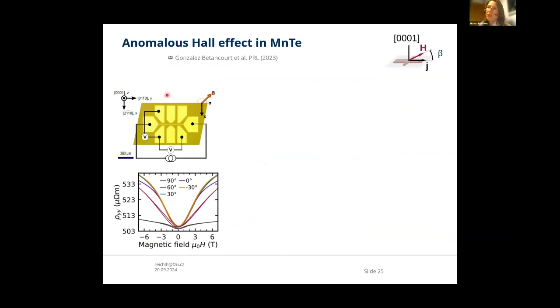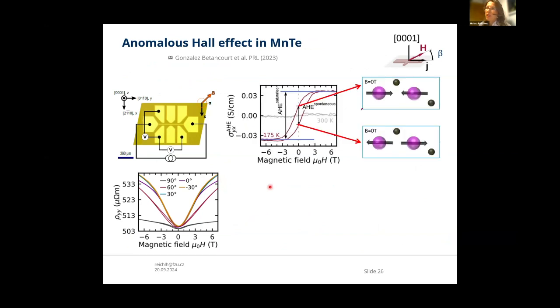Here we pattern Hall bars from the manganese telluride thin films, and we measure longitudinal and transversal response. In the longitudinal response, we see standard magnetoresistance or anisotropic magnetoresistance. I will mention it in a little more detail later. But what is maybe more interesting is the transversal signal. Here it's a sweep of the magnetic field with the linear slope already subtracted, so only the data after subtracting the ordinary Hall effect. What is important is that also in zero magnetic field, we observe a clear opening of the loop. We see a spontaneous signal, and also a signal saturating approximately around the spin flip field, as we expect.